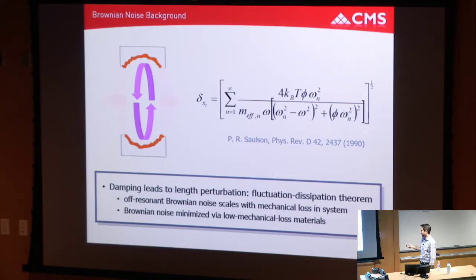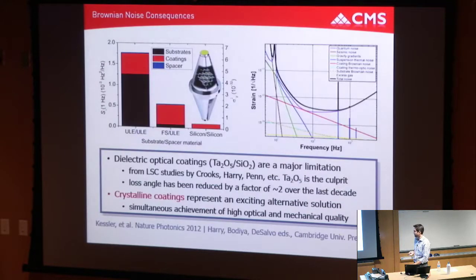And this work was really pioneered by LIGO, by this guy Peter Saulson from Syracuse. Basically, you have a contribution from every mechanical eigenfrequency in the system, and you're looking at the summation of all those off-resonant tails down at DC. So you can reduce the noise by reducing the temperature, operating at cryogenic temperatures. And also this phi is the mechanical loss angle, or the inverse of the mechanical quality factor in the system. Okay, those are the important points.